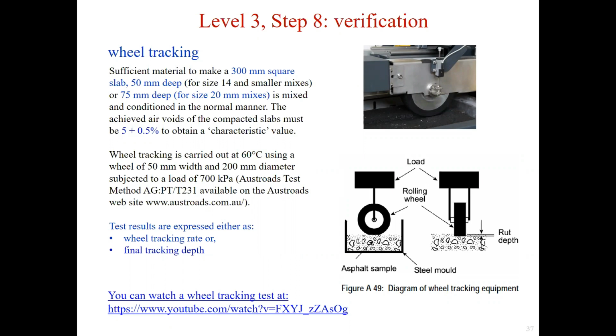For wheel tracking, normally a 300 millimeter square slab with 50 millimeter depth or 75 millimeter depth is made from the asphalt mix. The corresponding air voids of the slabs must be 5 plus or minus 0.5% to get a characteristic value.